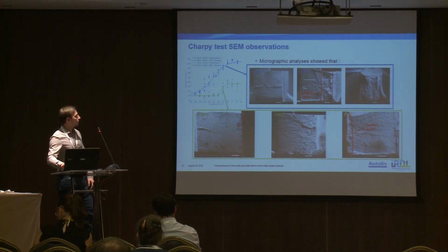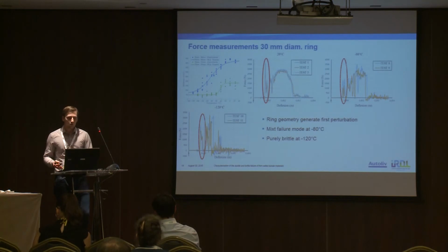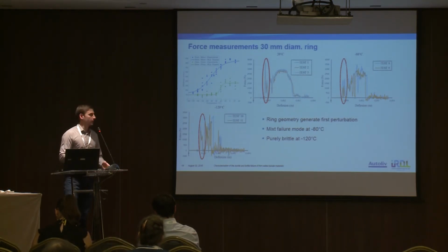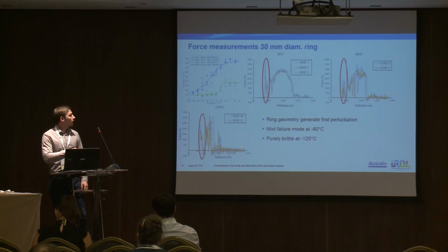Also, let's take a look at the result of the force measurement during a Charpy impact test. Here, I only used the result of the 30 millimeter ring diameter curve, and there is no classical force deflection curve for the Charpy impact test. But there is one phenomenon which is subject to discussion. What is this? It appears for each temperature, even if there is only brittle failure. And using numerical simulation, we were able to prove that this phenomenon is directly linked to the sample geometry.